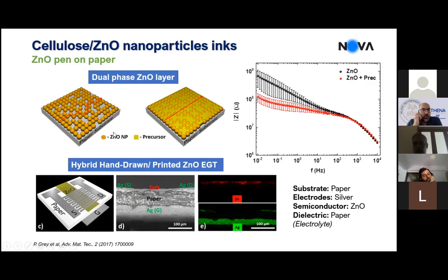And this layer that exists in between the nanoparticles has 2 main functions. Of course, the first one is to keep these nanoparticles together. Otherwise, you just blow on the paper and the particles will fly away. But also to improve the percolation paths in the written layer. Let's call it the written layer.